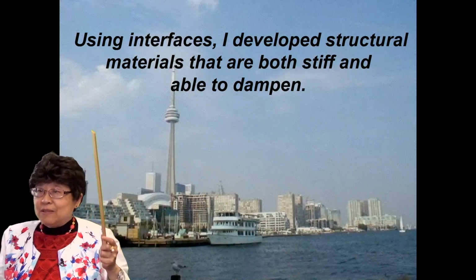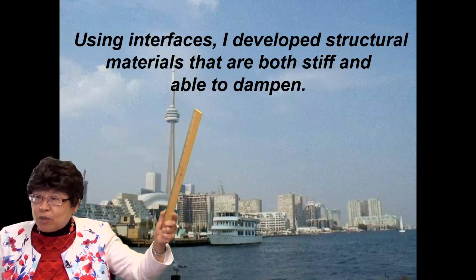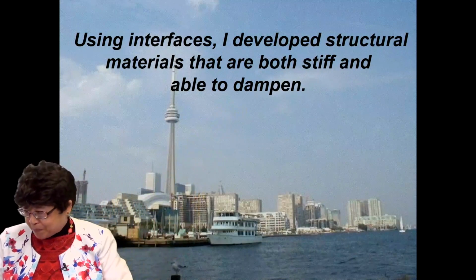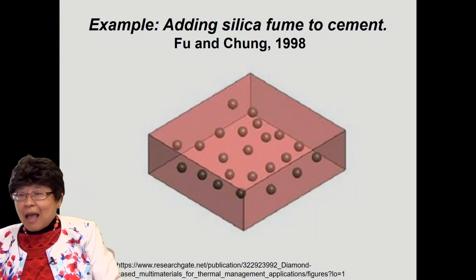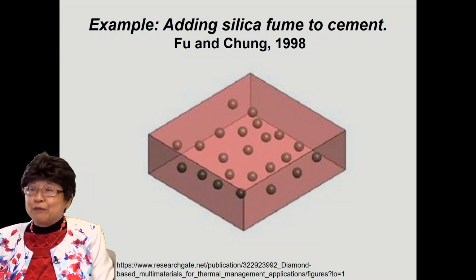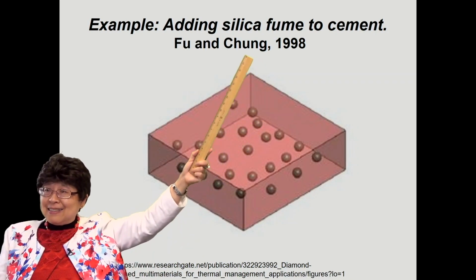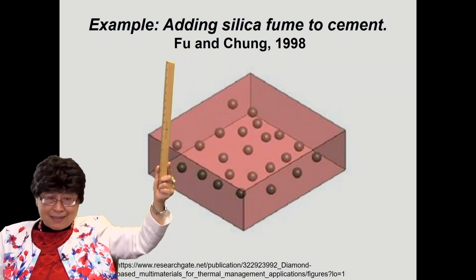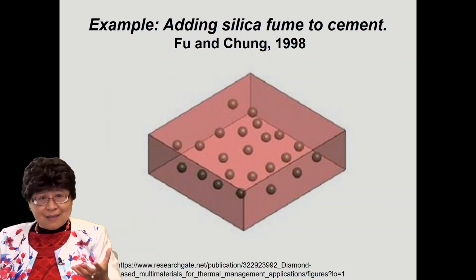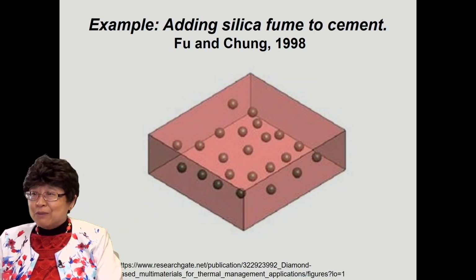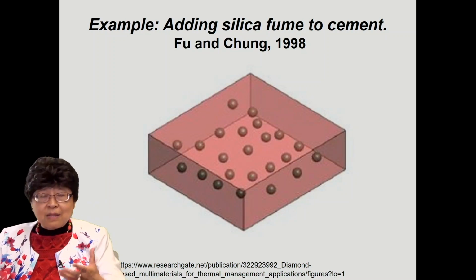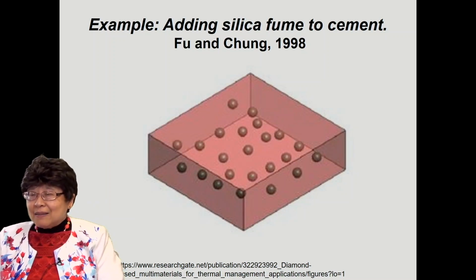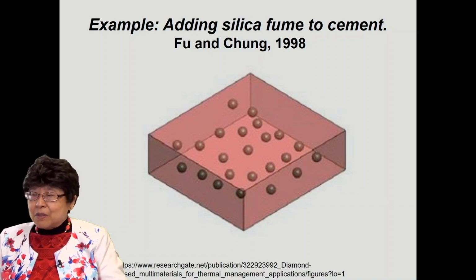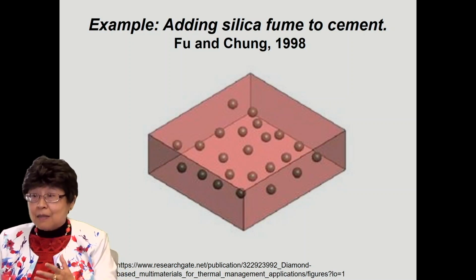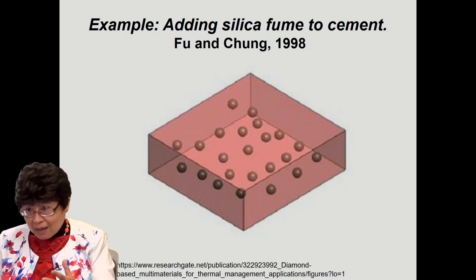So using the interfaces, I developed structural materials that are both stiff and able to dampen. An example, actually the first example that I provided to the world back in 1998, is adding silica fume to cement. Silica fume is tiny particles, mostly submicron, and one can add that to the cement mix. Because it's tiny, the presence of the silica fume particles gives rise to a lot of interface. It's the interface between the cement matrix and the silica.